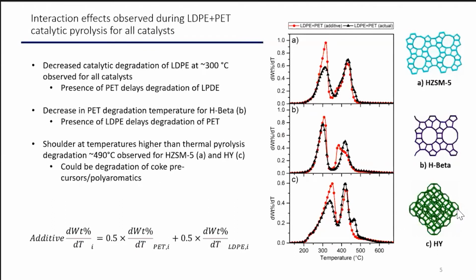And this shows that there is some interaction effects occurring between these two polymers during this catalytic pyrolysis. And we see that these interaction effects are similar for all of the catalysts. One that we see is that this degradation at 300 degrees C, which is corresponding to the degradation of LDPE, is decreased in magnitude for all of the catalysts, and it is believed that this PET is delaying the degradation of the LDPE.